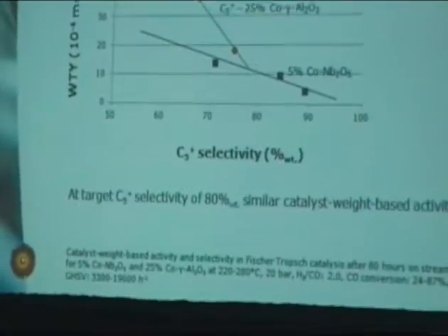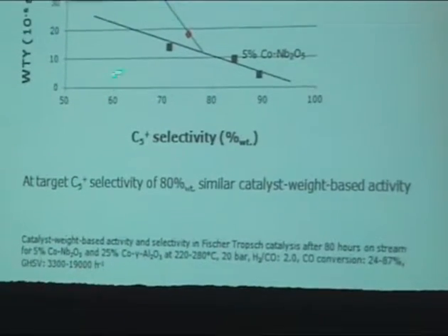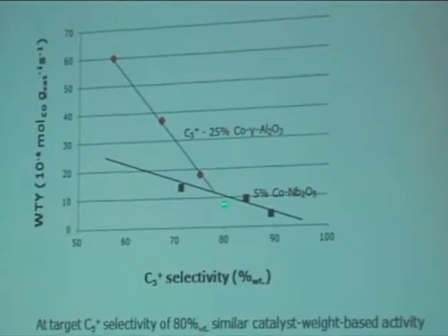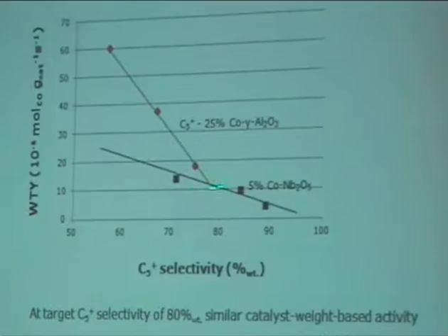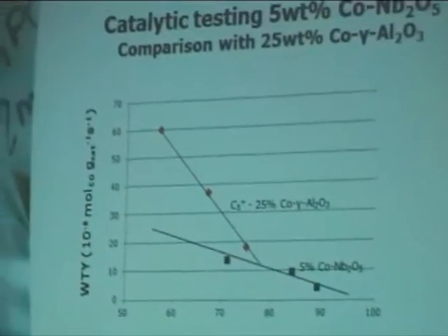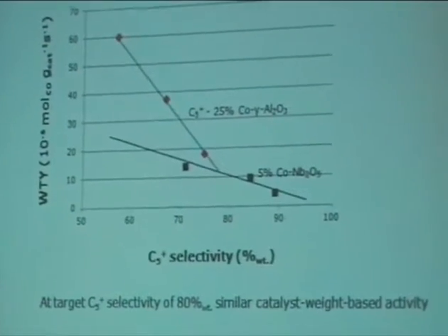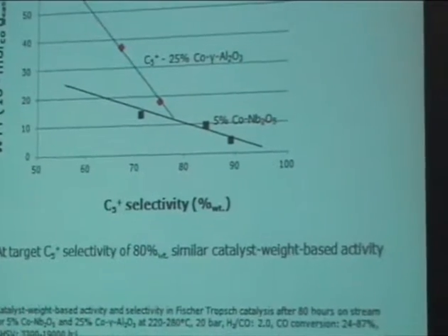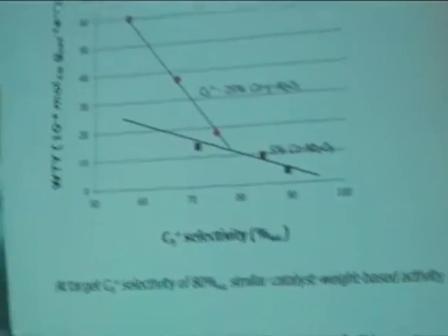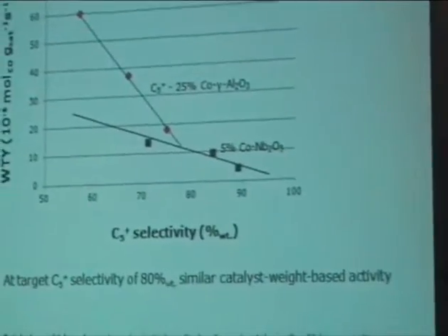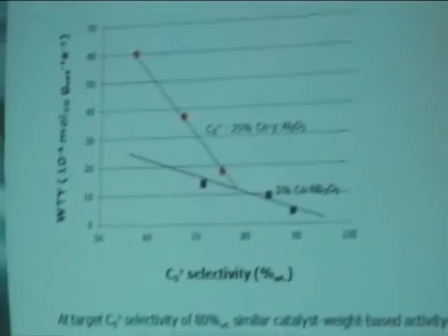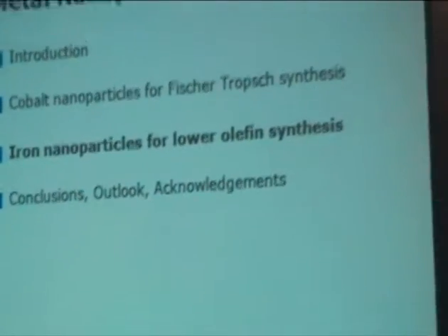And that's summarized in this plot. So if we take now the weight time yield, so per gram of catalyst on the vertical axis, and the C5 plus on the horizontal, and we take 80% as a target, you see that both catalysts more or less give the same weight time yield. In other words, I can operate cobalt niobium at higher temperatures, thereby compensating for the lower metal loadings. That was what I wanted to say about cobalt.